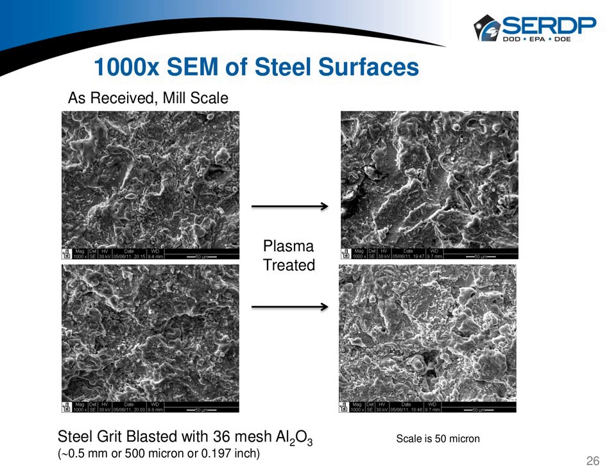Additional work we did was to look at both painted, depainted, repainted, depainted a second time surfaces. This particular slide shows scanning electron micrographs of various steel surfaces, pretty simple ones. This is the as-received mill scale that we saw earlier that was a dark gray in color. And notice that there's a lot of high topography or a lot of strong morphology here. It's not smooth by any means. There's also free particles from the mill scale as it's formed. And then once this surface is grit blasted, it becomes more uniform, if that's fair to say. It's still fairly random in terms of its surface texture.